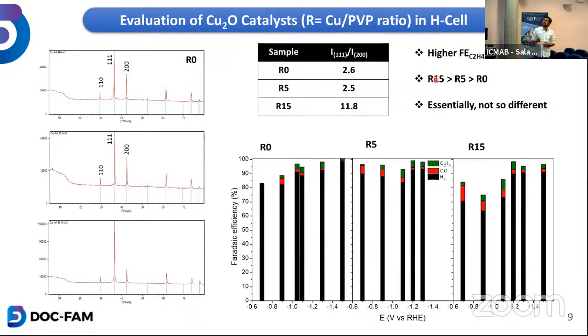So what I could see was that there is a higher Faraday efficiency for ethylene at -1.4 V with respect to the reversible hydrogen electrode, but these are the activities here for the ethylene. The R15 one seems to be quite promising, but it's not up to the mark, because this was done in a conventional H-cell. So the results were not so promising. It was kind of my initial days of getting into the work.